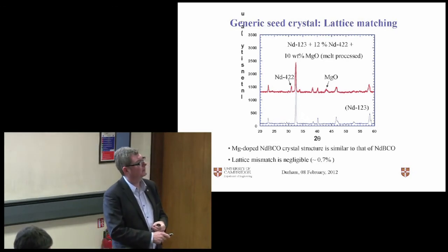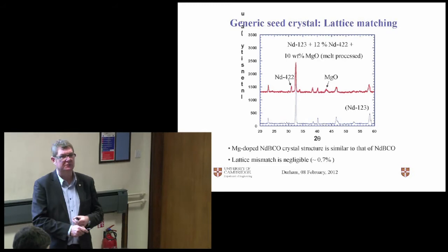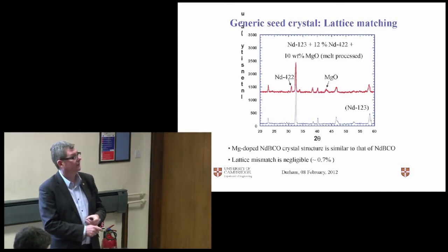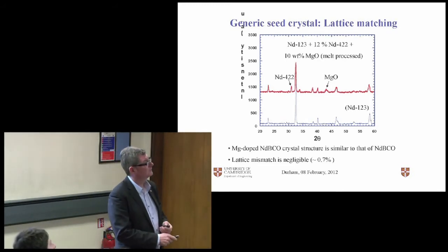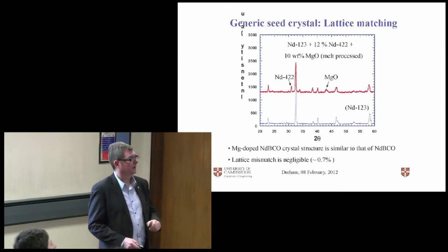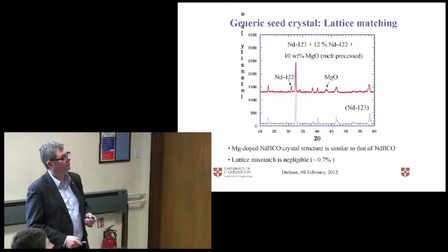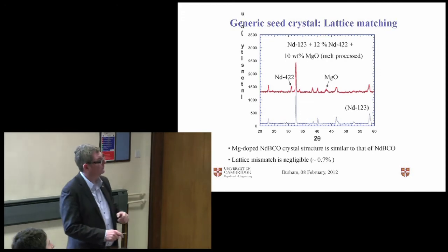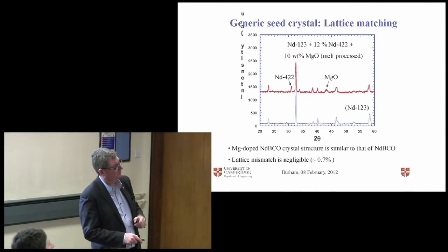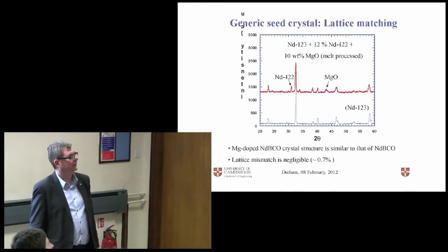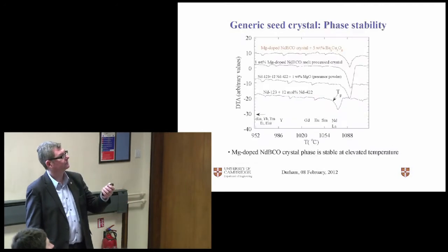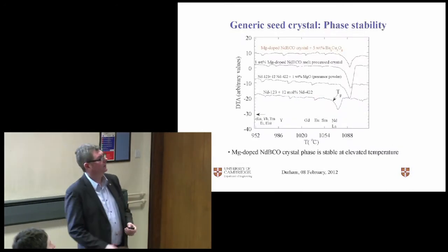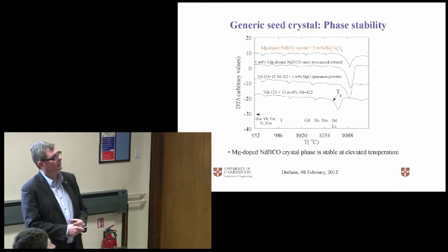The way that neodymium barium copper oxide was grown previously was using magnesia, and there's a 20% mismatch. And that gives you very low reproducibility in forming a single grain. But with the high temperature generic seed, we get this very good match between lattice parameters.